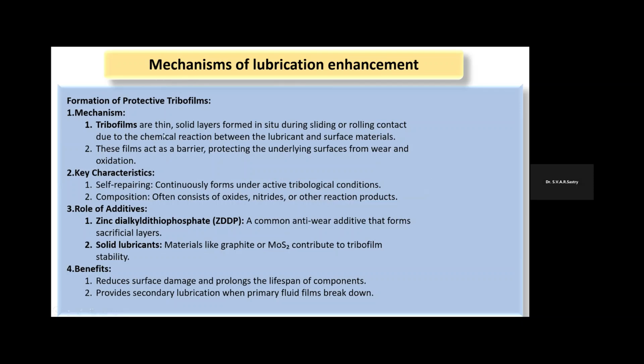Tribofilms are thin solid layers formed in situ during operation, during the sliding or rolling contact, due to the chemical reaction between the lubricant and the surface materials. These films, tribofilms, act as a barrier, protecting the underlying surface from wear and oxidation. The key features of these tribofilms: they are self-repairing, they continuously form under active tribological conditions, and they often consist of oxides, nitrides, or other reaction products.